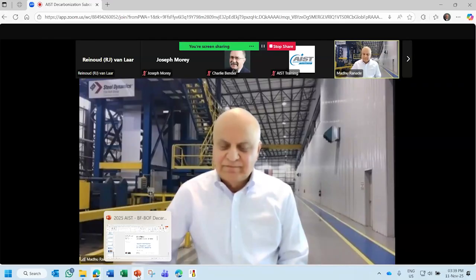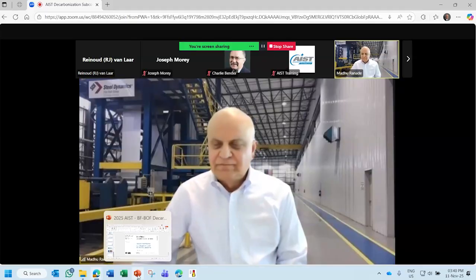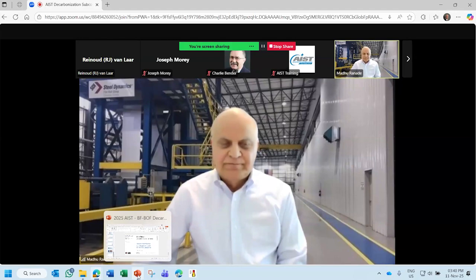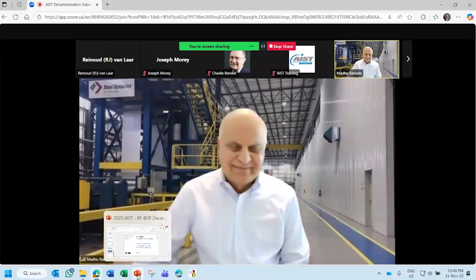Kobe Steel injected hot nitrogen. This is not a method we believe in; we believe it is a little bit more complicated. But interestingly, we also came to conclude already by our heat and mass balance model that, ultimately, but not in the next 5 years, the blast furnace could be used as a smelter when being charged with 100% DRI. And then the coke rate could be reduced to less than 100 if it would be a nitrogen blast furnace instead of an oxygen blast furnace. And I would be happy to share those results in another AIST seminar in another few years.